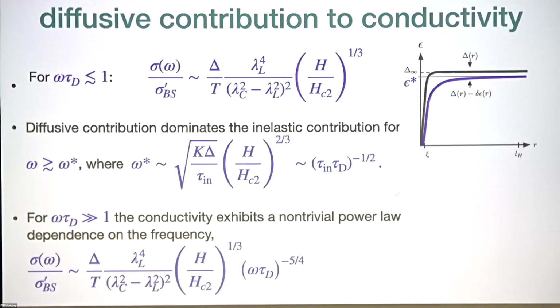Okay, then for frequencies below this characteristic energy scale for diffusion, you get this diffusive contribution to be frequency independent. And here's the expression. Again, the same ratio of London and Campbell lengths appears here. And you can ask, at what frequencies does this diffusive contribution become of the same order as the inelastic one? And this occurs at the frequency omega star, which is the geometric mean between the inelastic relaxation rate and the diffusion rate across the vortex core. And at higher frequencies above the diffusion rate, you get a decrease with frequency with this non-trivial exponent 5/4 arising again from this sensitivity.